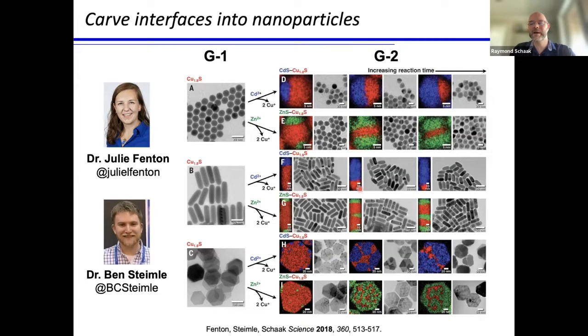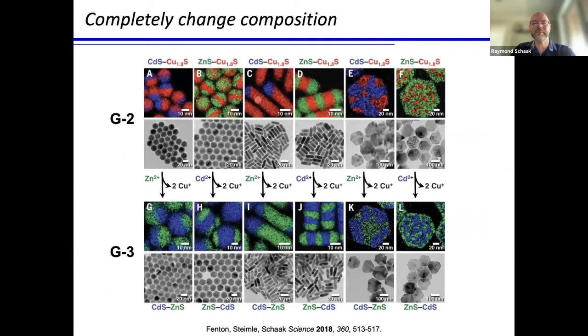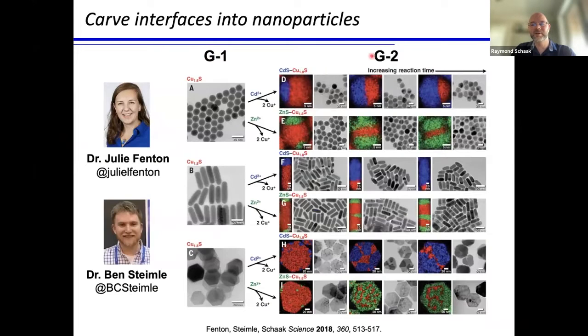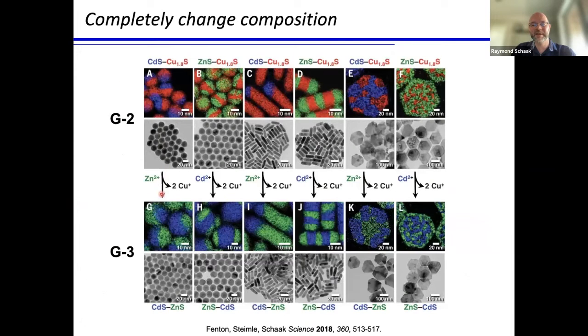But there's still remaining copper sulfide, and copper sulfide is the material that exchanges. So if we take this central group here, and that's what's shown here on the top, all of these examples have remaining copper sulfide in them. So if the first exchange that we did going from this first generation to second generation was with cadmium, we can do a second exchange with zinc to replace the remainder of the copper with zinc. And likewise, if we started with zinc as our first exchange, we can replace the remaining copper with cadmium.